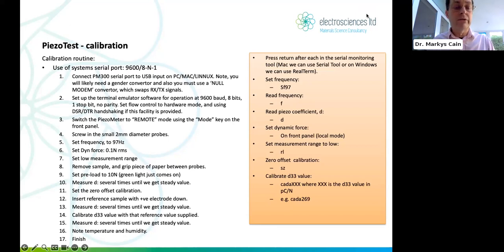Anyway, so once you set up the serial port, you switch the piezometer to remote mode, and you can start doing some measurements. And then, of course, every time you press D, return, you can read in the D coefficient. Okay, and that's fine. You can also then put a reference sample in, and you can measure D several times, and that will then be theoretically your calibrated value, which you then write back to the unit, whatever it is, because you're using quartz, for example, or lithium niobate, for example.